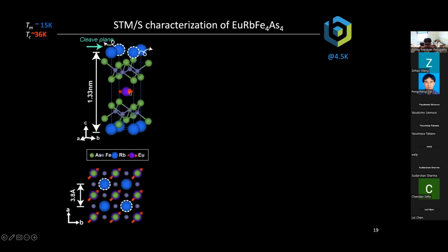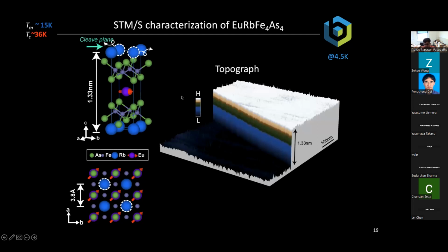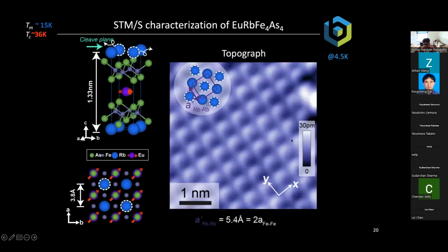And so the magnetic layer in these measurements is actually hidden to us. It's kind of two levels below where we scan. And all the implications about magnetism, we don't directly measure magnetism in our experiments. We just measure the local density of states with STM measurements. And so when you cleave this material, it cleaves quite nicely. It gives you flat surfaces. And between these flat surfaces, you can see unit cell steps. So 1.33 nanometers is the unit cell height of this material. And if you zoom in, you can see atoms of the material and so on.